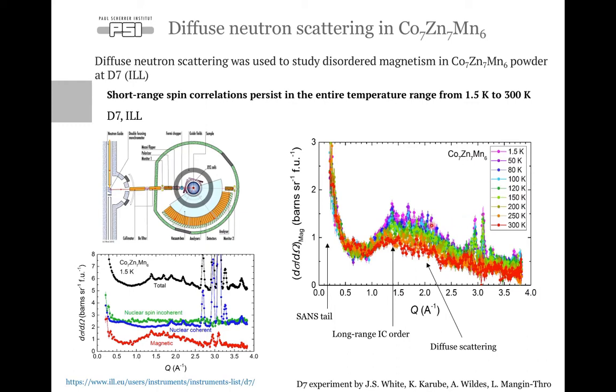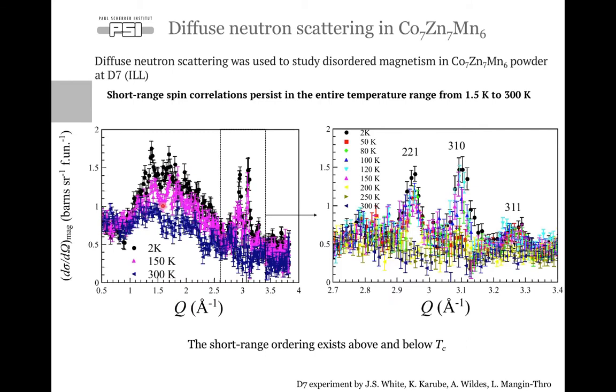And the short-range correlations correspond roughly to the distances between manganese ions in the hyperkagome site. Practically, the only difference that can be observed between low temperature, intermediate temperature, and high temperature diffraction patterns is that the magnetic scattering is enhanced due to the enhancement of the magnetic moment at the base temperature, and it's thermally suppressed at around 300 K.